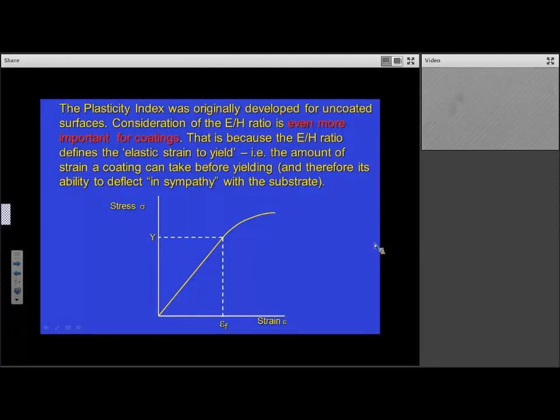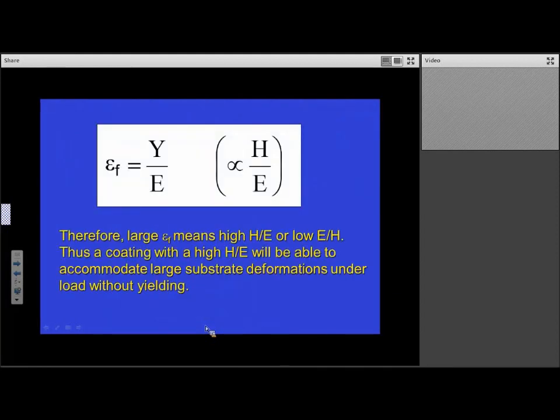That's because the E/H ratio defines the elastic strain to yield. That's the amount of strain a coating can take before yielding, and therefore its ability to deflect in sympathy with the substrate. So you know that if you take the stress strain curve, the slope of the stress strain curve is the elastic modulus. So E is equal to Y over the strain. In this case, the limiting yield stress is Y, and the limiting strain at the point of yield is epsilon F. So E is equal to Y over epsilon F. So epsilon F is equal to Y over E. Since Y is directly related to hardness, typically hardness is 3 times yield stress for most surfaces, you can see, therefore, that the elastic strain to yield is directly related to the ratio of hardness to the modulus. So that's one reason why H over E is important for coatings.